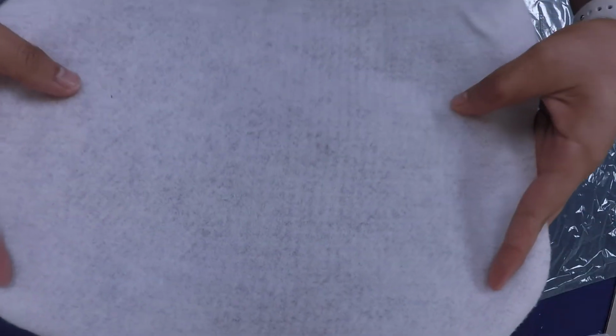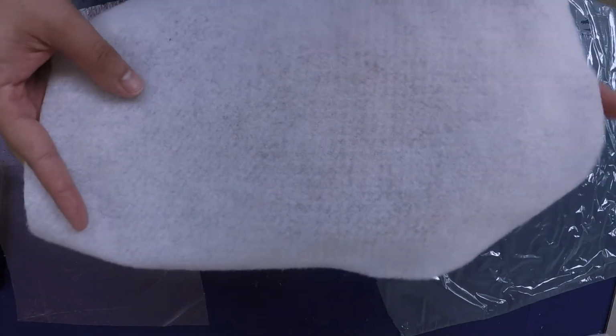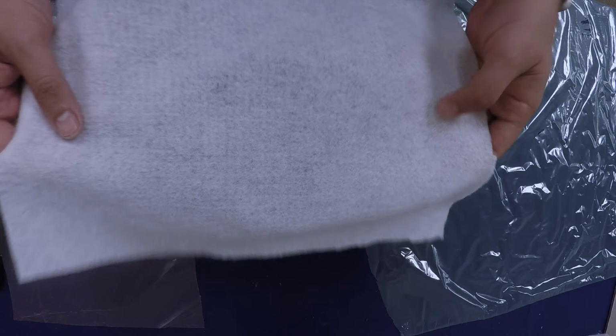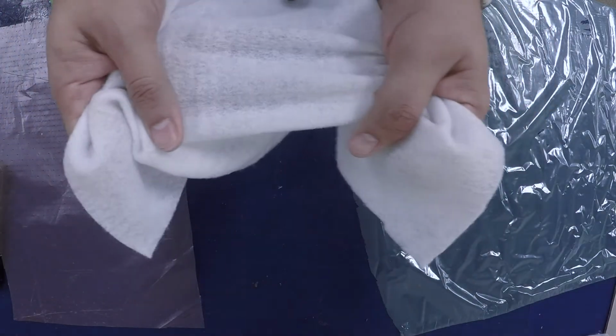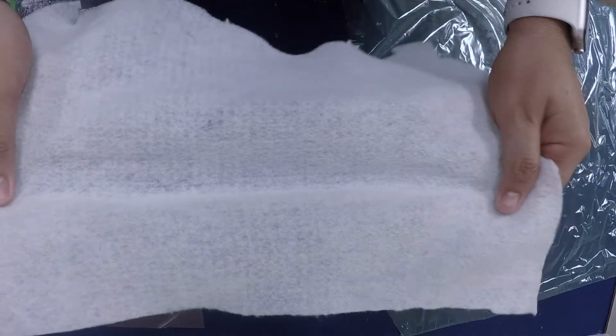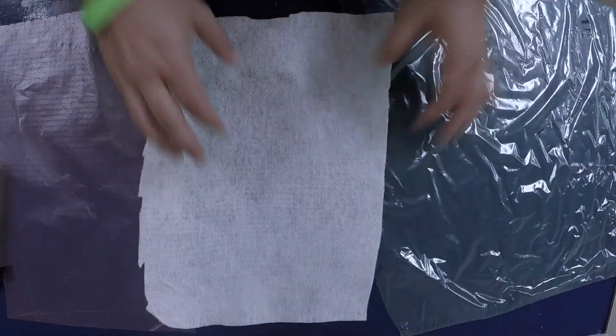The next film is the bleeder, and its purpose is to allow both air and gas to travel from any location in the layup onto the vacuum port to be sucked out, as well as absorbing any of the excess epoxy that travels through the release film. In a complex layup, these two functions will need to be separated into two different layers of material, since the absorption of the excess resin will begin to impede the flow of gases.